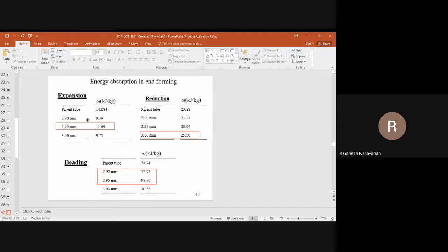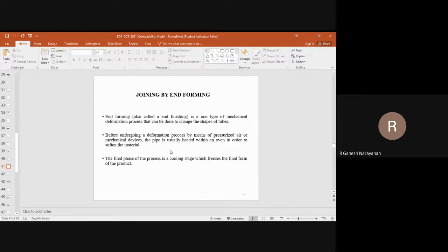See, this is one example where the plunge depth is of the order of, let us say, 2.9 mm, 2.95 and 3 mm, and you can see the energy absorption has been evaluated and compared with the parent tube in expansion, reduction and beading. And you will see that they are approaching that of the parent tube. In one case, it is less. In the other case, it is better in reduction. In beading, it is also closer to that of your parent tube, which is a good development from the point of view of using friction stir welded blanks.